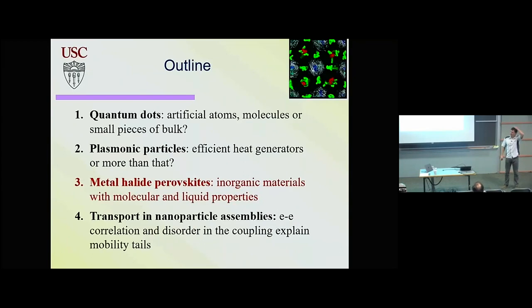I'm not sure about surface, because this happens not just because of rotation of the organic molecule. If you have inorganic cation, you also have pretty large polarons. And surface maybe creates extra flexibility, so that can also have an effect. But basically you reduce the size of the polaron, which increases Coulomb interactions. And that's why they emit well, actually. In principle, the competing energy scales are the exciton binding energy, which increases with decreasing size, and the reorganization energy, which has the same trend.